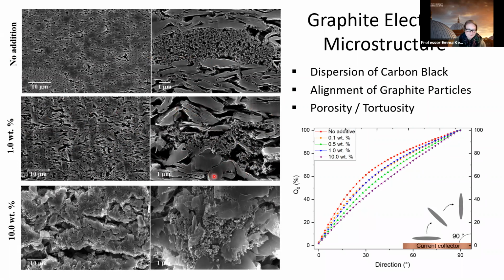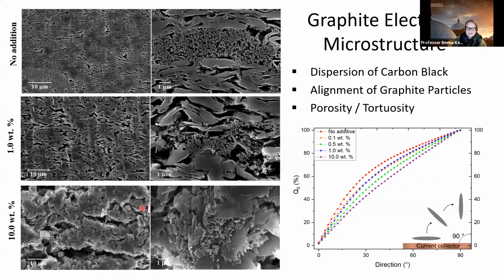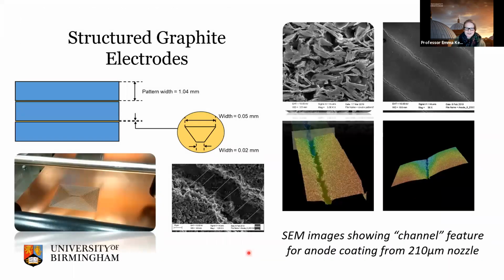to the current collector. We put a 10 weight% in, and although we got quite a big change, you can see here in your microstructure, you actually got a collapse in a way of your microstructure, and you started to get agglomerates of your systems instead of nice dispersion with good porosity. So huge porosity and then not so big porosity. But we did have less alignment of the graphite in this system. And these are just some of the graphs to show you how we could optimize some of these electrode properties.